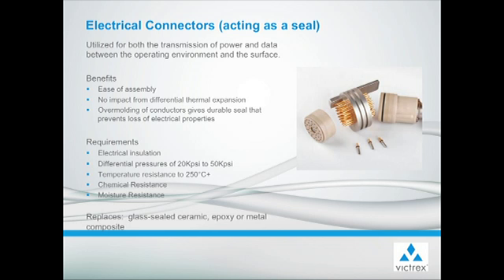Some of the key engineering requirements are electrical insulation, differential pressures of 20 to 50,000 psi, temperature resistance to 250 degrees C and greater, chemical resistance to downhole corrosive chemicals, moisture and hydrolysis resistance, and these are typically replacing glass-sealed ceramic, epoxy, or metal composite connectors.